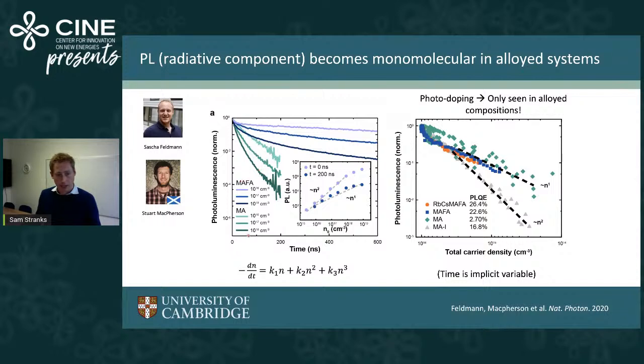So this is looking at, again, over time, the photoluminescence. And we see the methyl ammonium lead iodide kinetics here. But as soon as we add the formamidinium, we see the lifetime increases really quite dramatically. And this is quite consistent across even different excitation densities. And when we look at this, what we see is this first component, then there's this really long, what looks like a plateau on these timescales.